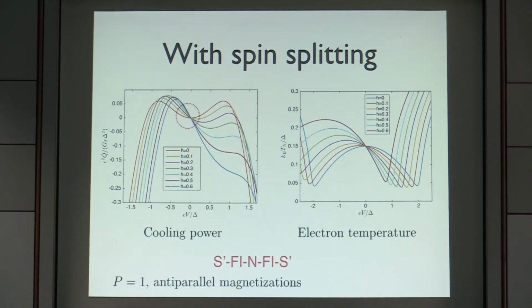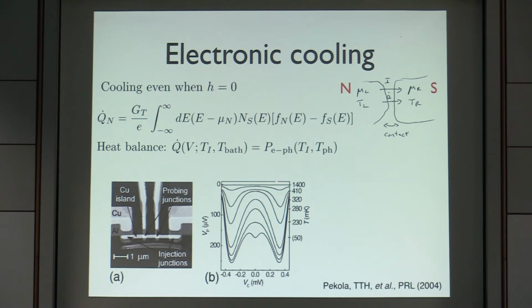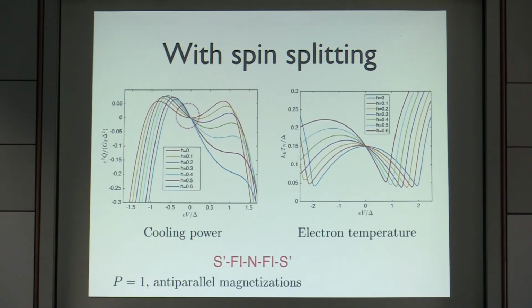Now, in the presence of the exchange field, these cooling curves lose their symmetry. What you can see here is that at linear response, nothing happens in this SINIS case. You actually have to apply a voltage of the order of the gap to see something. Now, with spin splitting, the curves tilt, and you get something at linear response already, which is basically what I discussed before. You can of course study the nonlinear response also in this case.